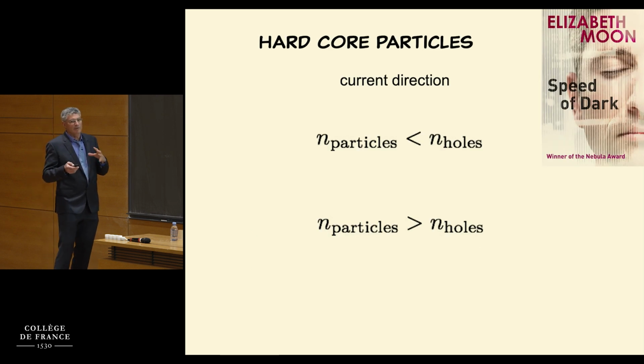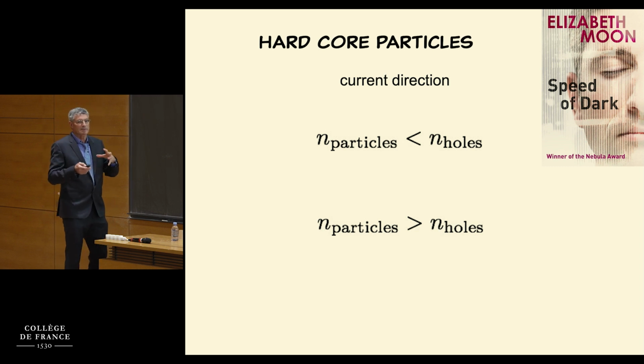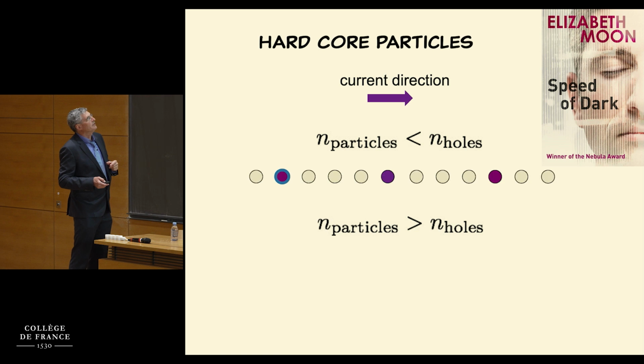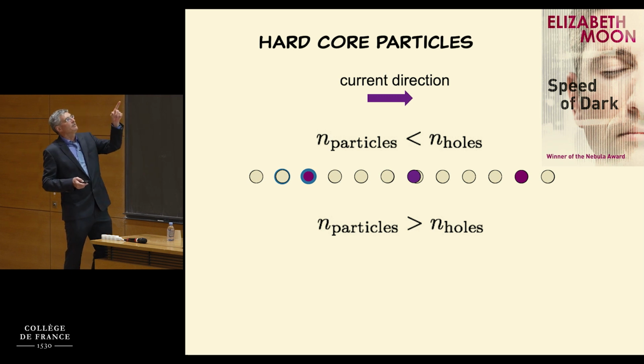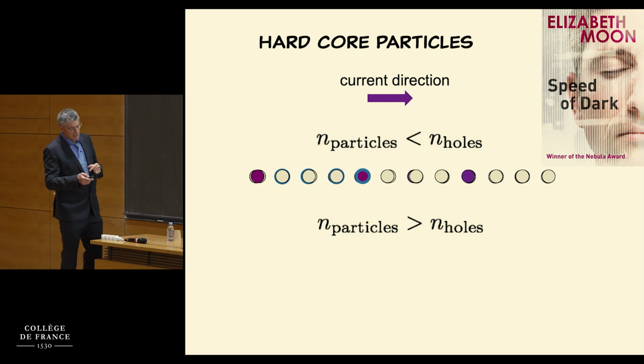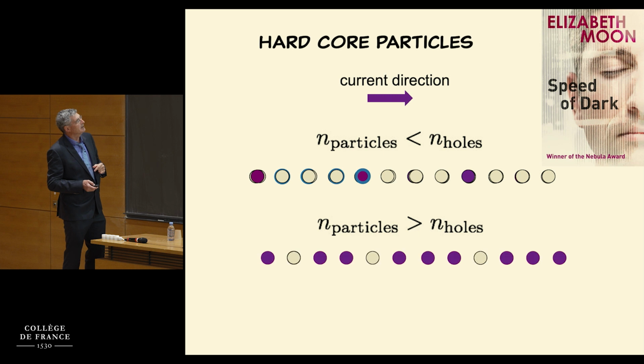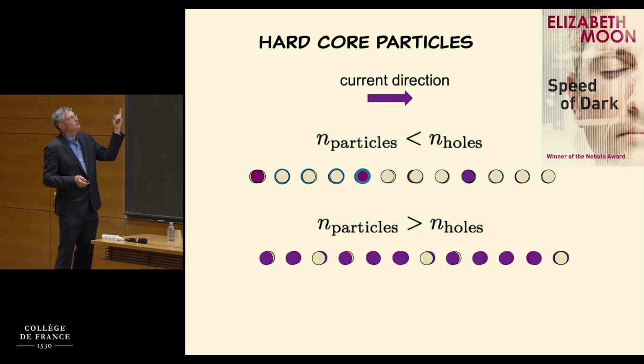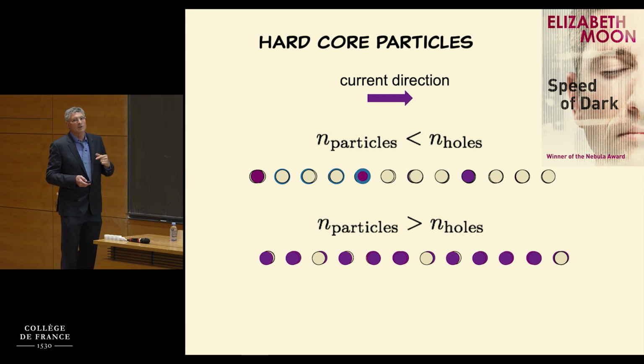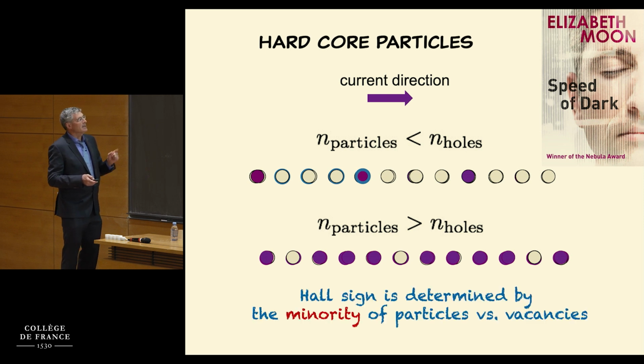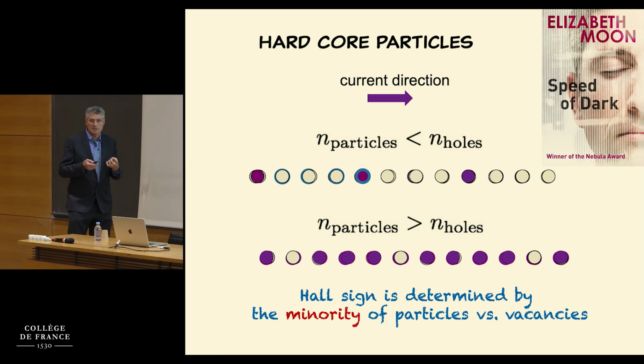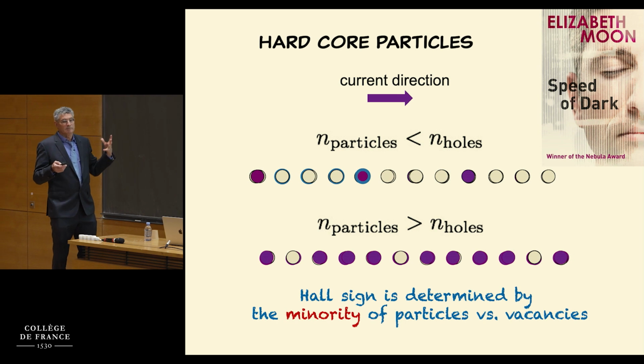Because if you want to get the bottom line of all this picture, you have particles, and it doesn't matter now if they're fermions or bosons. There's strong interactions between the particles, and they induce hardcore constraint. So if you think about hardcore particles moving, then you see that if you have a minority of sites occupied, then the motion is carried by the particles. But if you look at a system where there's more particles than holes, and you move the particles, then now you see, to your eye at least, that what is moving are the holes to the left, which is the same current, but that's really what the Hall effect is doing. It tells you what are the minority carriers in this case. So the Hall sign is determined by the minority of particles versus vacancies when you have this Mott physics, this interaction physics dominating, and not, let's say, band structure physics.